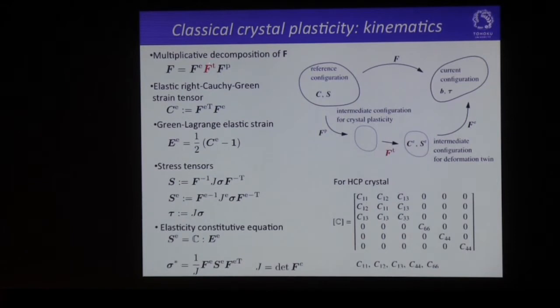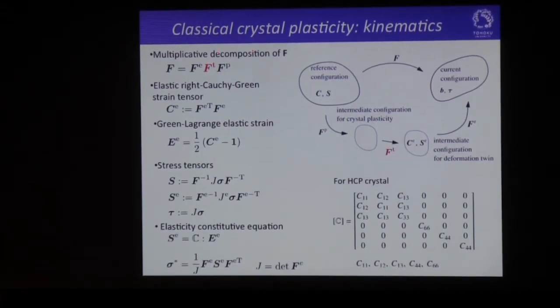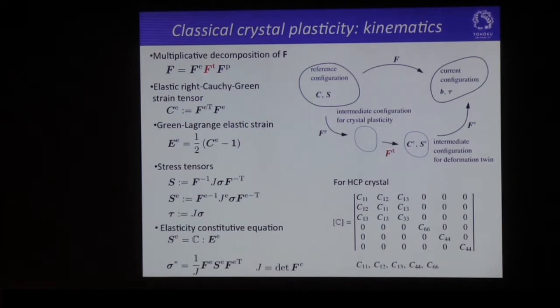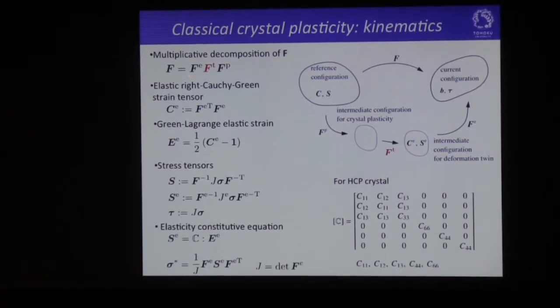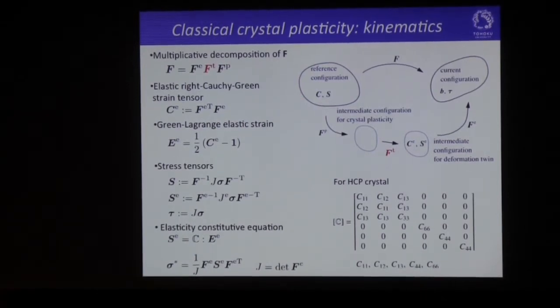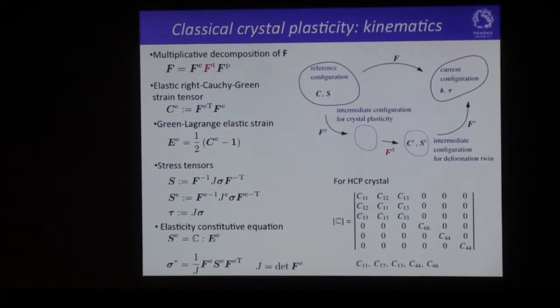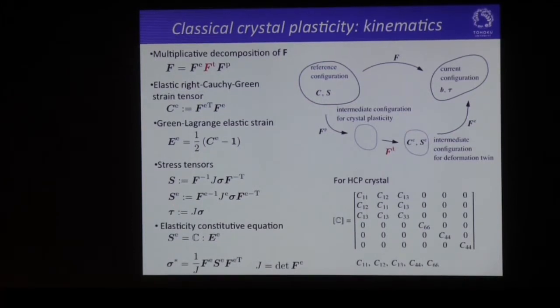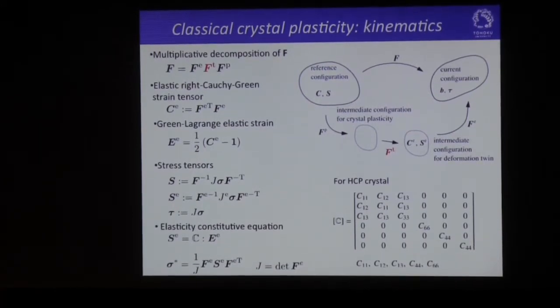So in order to do that, I will introduce the deformation gradient for the twinning deformation here. This is the twinning deformation gradient between the elastic and plastic component of the deformation gradient. All the other equations are the same as the classical theory of crystal plasticity, so I will skip most of the equations associated with the crystallographic slip.